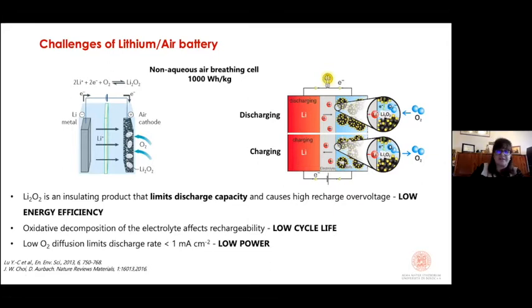Third, the oxygen, which is the active component, spontaneously goes to the porous carbon and diffuses very slowly, because it's a spontaneous transport from the environment to the cell. And this slow process limits the discharge rates of the cells, so a low power.